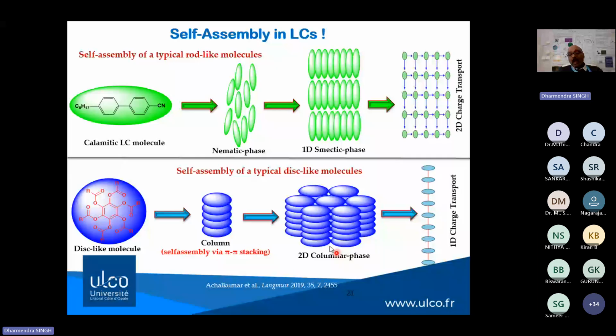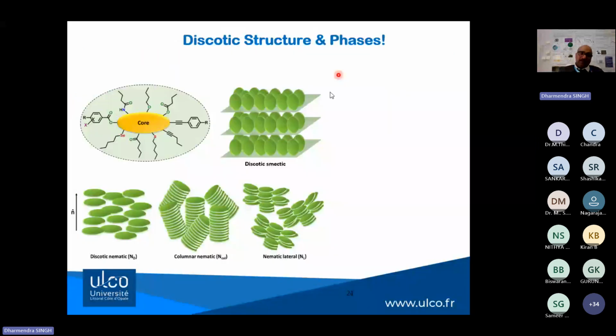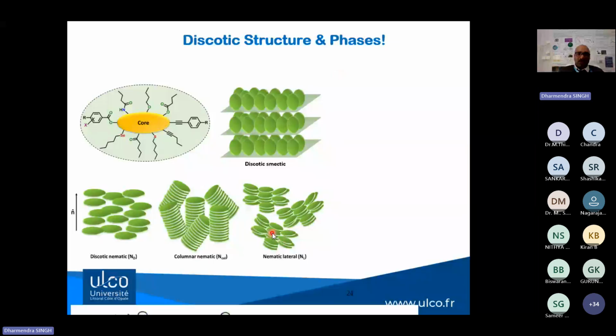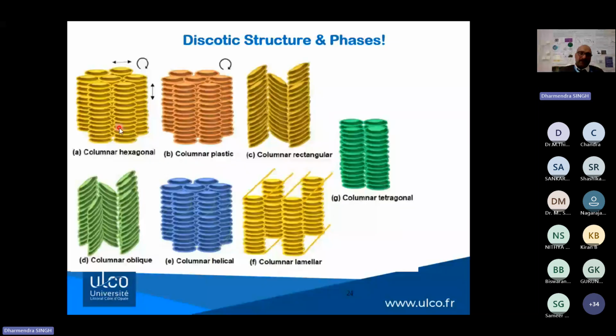And as these phases are formed, 2D columnar phases, in 2D columnar phases, one-dimensional charge transport takes place. So there can be different phases of this discotic material, like they can be arranged in the nematic orientation, in the columns, and so on. And depending on the crystallographic conditions, as I explained before, they can be arranged into different phases like hexagonal, plastic, rectangular, helical, oblique, lamellar, and tetragonal as well.